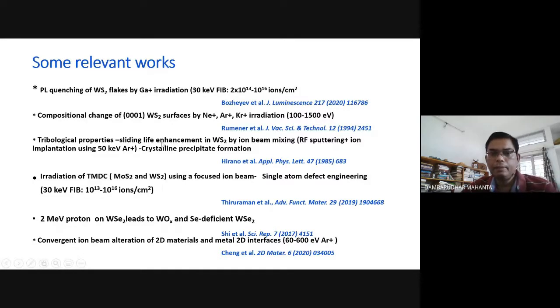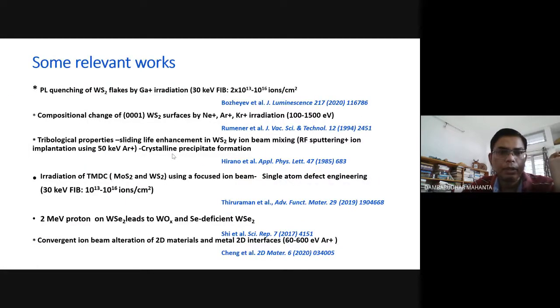So sliding life enhancement was found because of ion beam mixing. Ion beam mixing means first RF sputtering followed by ion implantation. Now another material, TMDC, MoS2 and WS2, molybdenum sulfide and tungsten sulfide, using focused ion beam. So in this case, single atom defect engineering was possible, as suggested by the author.